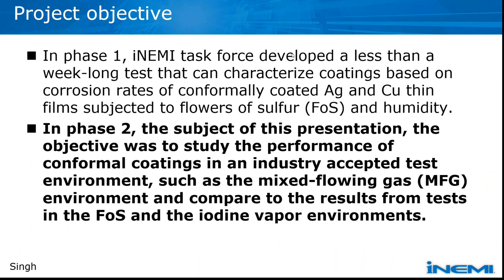In phase one, we developed the technique using flowers of sulfur and humidity as a corrosive environment. Phase one was successful, but flowers of sulfur is not the industry standard - mixed flowing gas is the industry standard. So in phase two, we're comparing the flowers of sulfur results with those from the mixed flowing gas environment, and we include iodine vapor as the third environment. We're comparing all three to see how they perform in evaluating conformal coatings.